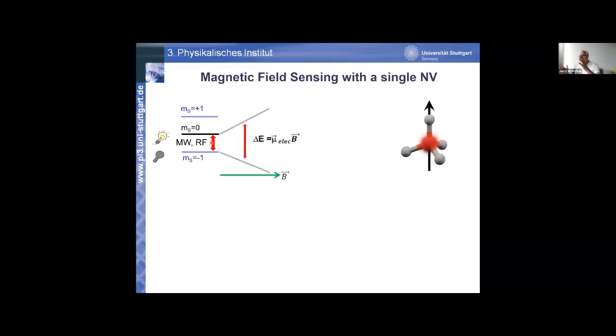And of course, if you apply a magnetic field, you then measure the Zeeman effect, and the spin splitting here is proportional to the magnetic field. If you assume that the mu of your electron spin is constant, which it is in our experiments, so the g factors are very constant, then essentially you get a calibration-free measurement of magnetic field. I should say that there is some anisotropy in the system, so you have preferential alignment of the electron spin given by the crystalline lattice. So essentially you have the capability of doing vector magnetometry. That is, you can also measure the orientation of the magnetic field.